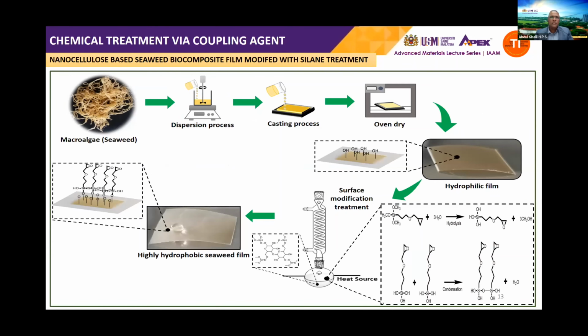The next slide is on the enhancement of seaweed through chemical treatment. In general, the enhancement using chemical treatments can be achieved, especially like a coupling agent and hydride modification, compatibilizer enhancement, and etc. A previous study has shown that the application of coupling agent silane can impart improvement in physical, mechanical, and chemical properties. Therefore, in this study, we use tri-ethoxymethylsilane for the surface activation of seaweed nanocellulose film. Silane acts as a bridge that modifies the active site of OH group on the surface of a seaweed nanocellulose.